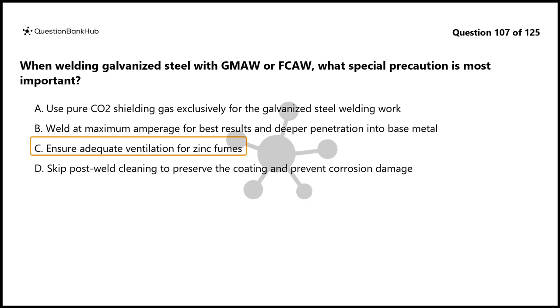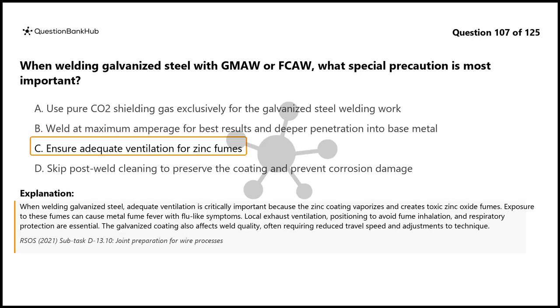The correct answer is C. Ensure adequate ventilation for zinc fumes. When welding galvanized steel, adequate ventilation is critically important because the zinc coating vaporizes and creates toxic zinc oxide fumes. Exposure to these fumes can cause metal fume fever with flu-like symptoms. Local exhaust ventilation, positioning to avoid fume inhalation, and respiratory protection are essential.